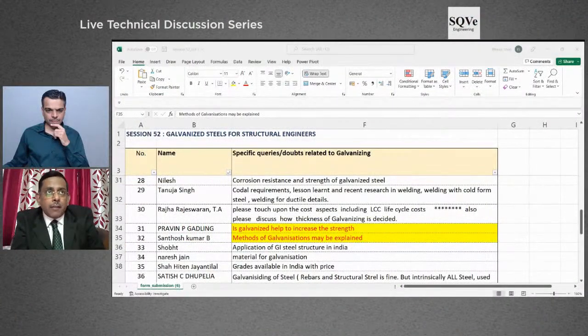In continuous galvanizing, dipping is only a few seconds. But in the case of batch galvanizing, it may be a few seconds to minutes based on your requirement. And then it is dipped completely in the bath. After a few minutes, you take out the samples, which will be solidified. Then you do some cooling process so that you get rapid cooling and a zinc coated surface. This is the batch galvanizing process.